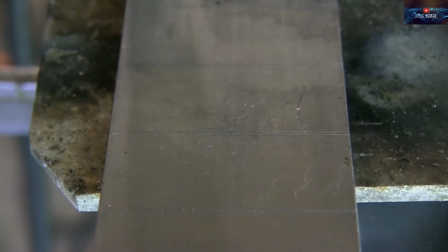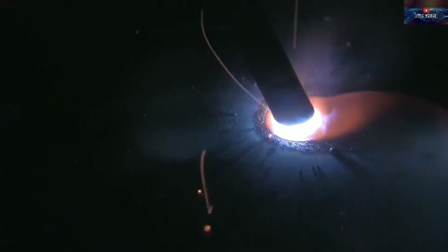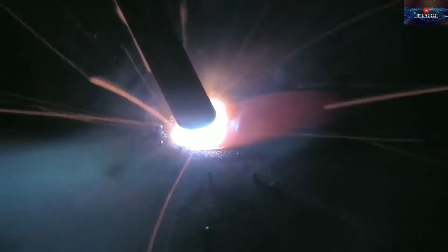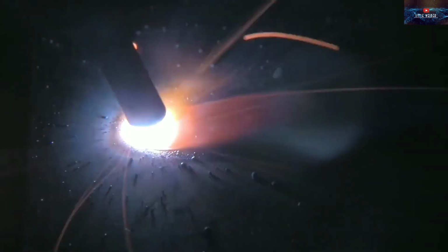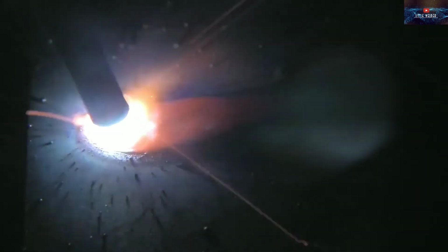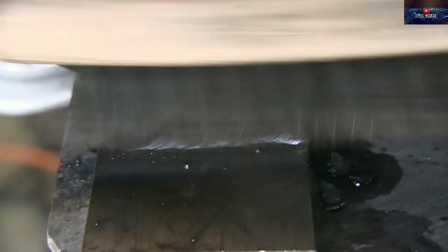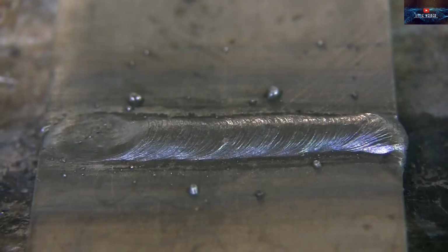Let's get ready. Strike the arc on the edge of the material just like you would strike a match. Try to maintain a fairly tight arc length. When I say fairly tight, I mean the diameter of the electrode or less. That's the core of the electrode, so that's 1/8 of an inch. Arc length can be deceiving. It's usually longer than you think it is because the wire is burning off up inside that flux.